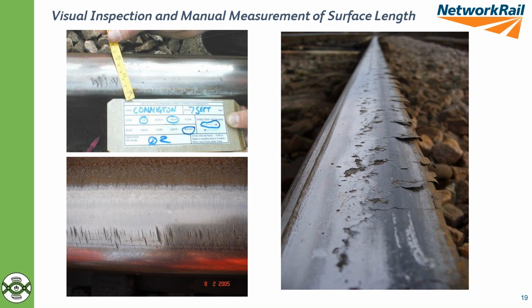The top left picture, very isolated but associated with a weld. Small change in the profile, perhaps a change in the metallurgy locally at the weld, but a very short patch of RCF, which if left untreated will go on to cause a defective rail and in due course potentially a broken rail. Picture on the right, low rail damage, low rail of an overcanted curve used by heavy freight, and you can see the physical extrusion off the surface that spread towards the field side of the rail,